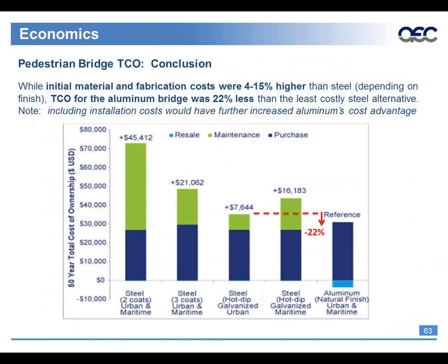So total cost of ownership, initial material and fabrication costs were higher with the aluminum than with the steel. The total cost of ownership for the aluminum bridge was 22% less than the least costly steel alternative. And once again, installation would have further taken into account the advantages. And so, the aluminum costs you more up front, but essentially once you put it in place with the proper fasteners and everything else, you didn't have to do anything to maintain it. With the corrosion resistance of the bridge, you didn't have to do anything.